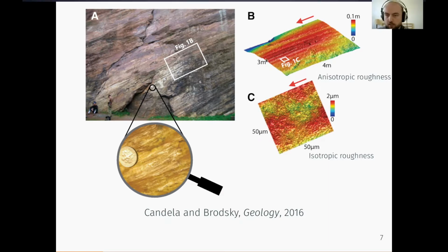And so you can clearly see the sliding direction in the anisotropic roughness. But if you zoom in and you look at the roughness at the micro scale, the anisotropy disappears and you have isotropic roughness. So there's clearly a physical phenomenon here that's at play with a characteristic scale that distinguishes between microscale here and meter scale in this case.